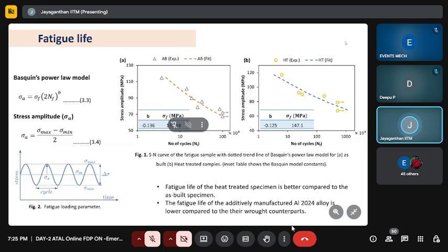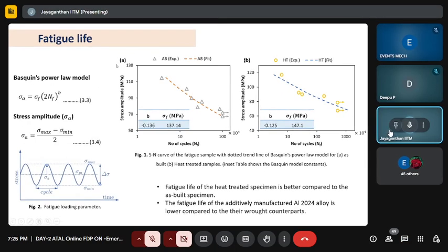To characterize high cycle fatigue, we use this Basquin model. Rather, we try to highlight stress versus number of cycles to failure. You can see from figure 1, the S-N curve is nothing but stress versus number of cycles to failure. Having plotted your experimental data, I fit it using the Basquin power law model. Stress amplitude is connected to sigma f', the fatigue strength coefficient. N is number of cycles. b represents the strength exponent. So we have the values of b and sigma f' having fitted this experimental data to this power law fit.